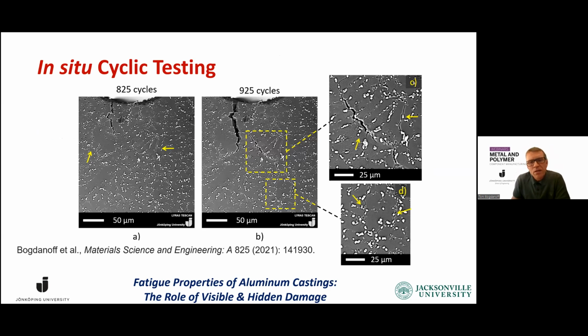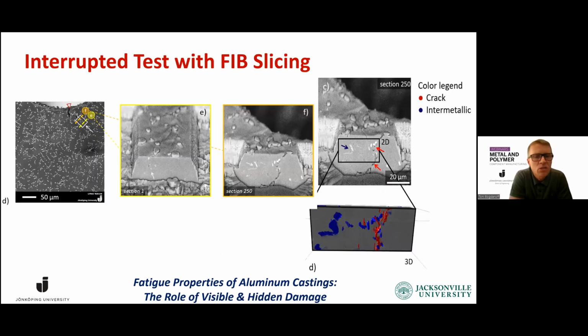So what we did was an interrupted test where we let the crack propagate for a while. And then we decided to stop it. So we actually can do an interrupted test. And then we used our SEM to do FIB sections. If you take the next slide.